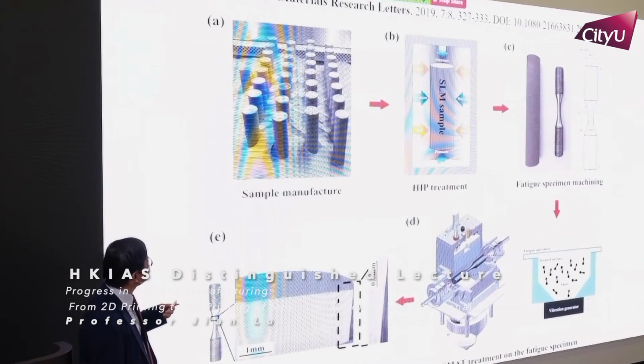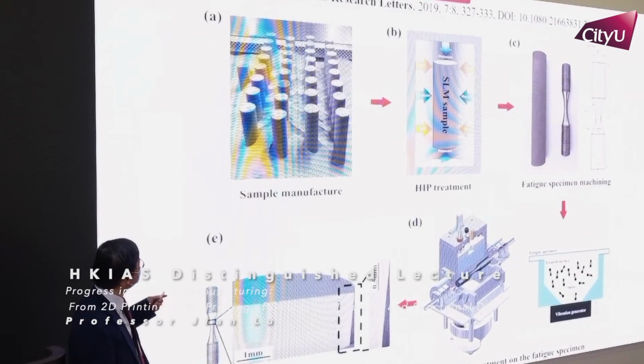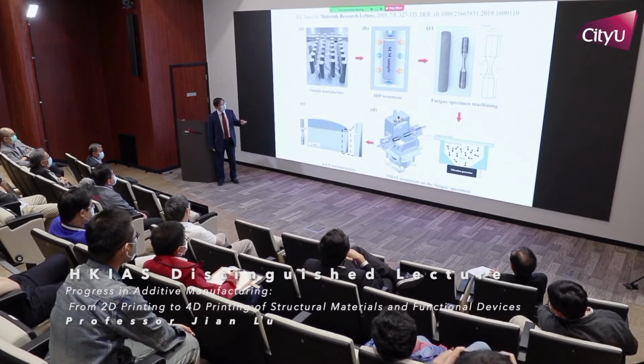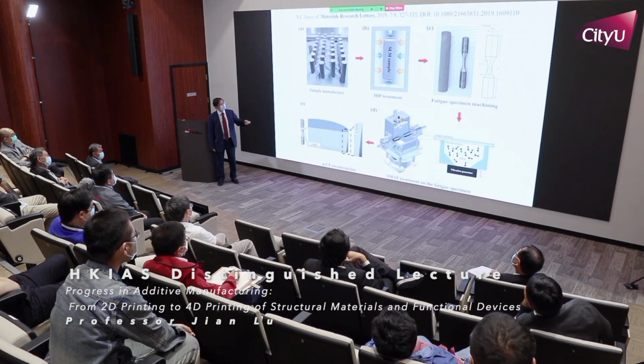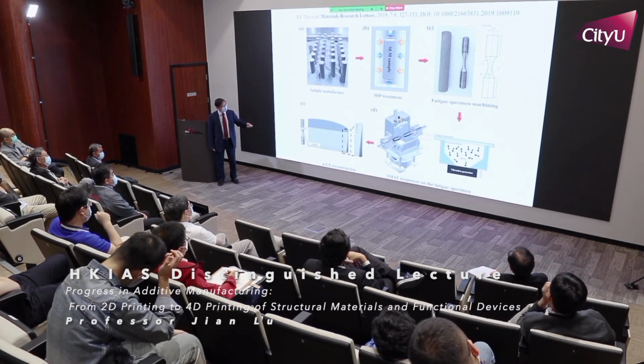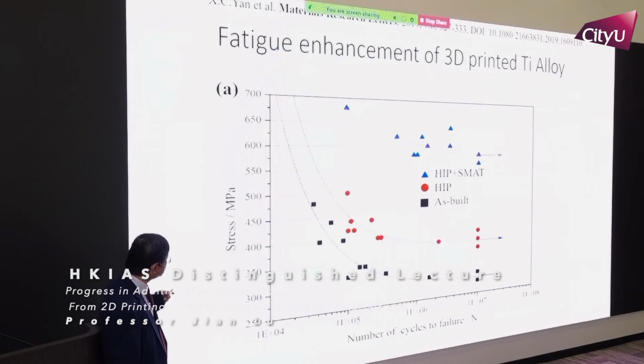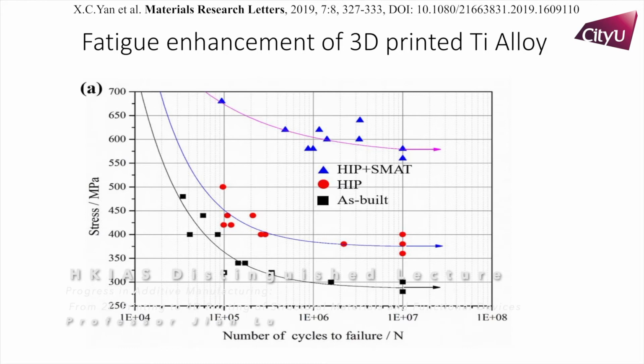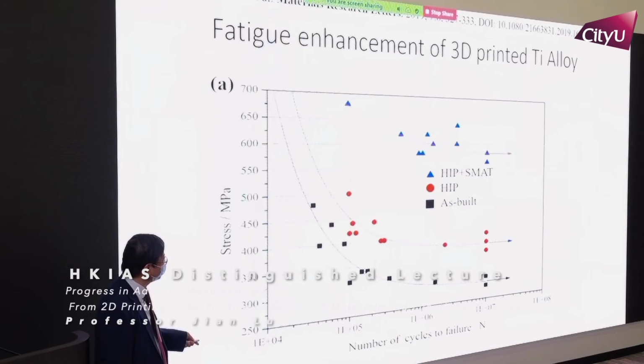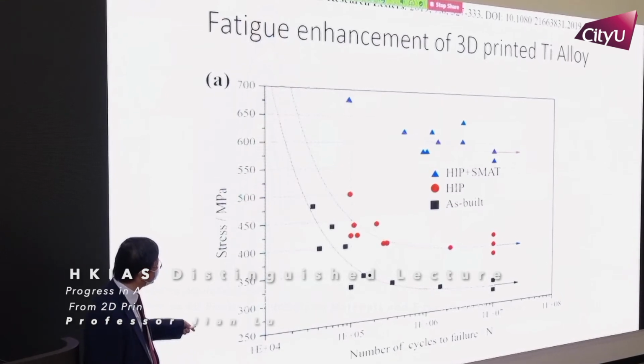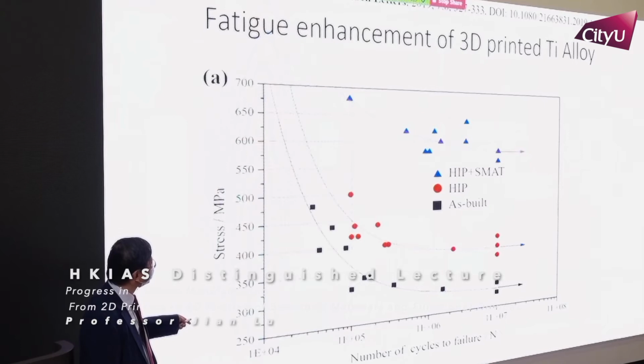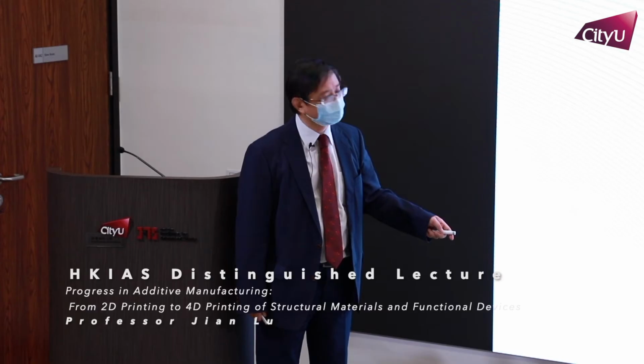Okay, so this is to show the feasibility of this structure. So we 3D print the fatigue sample with HIP treatment. We densify the material and we prepare the fatigue sample, and then we treat this fatigue sample using this technology, and then you can see, compared to the as-built, so normal 3D printing, the fatigue strength is only, say, 280 MPa, and then if we use HIP, it's here, a little bit better, okay? But if we use HIP plus SMAT, you can see we can roughly double the fatigue resistance.